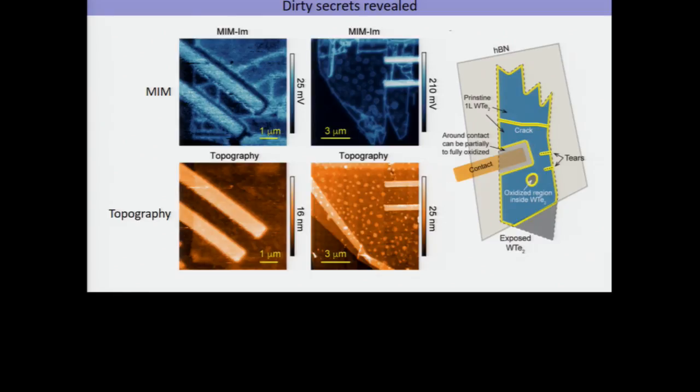But what prevents you from etching and then putting the contacts on, some sort of fab, etch, contact? There's a lot to be said about how to fab these devices, but the main limitation is you have to prepare it. The WTe2 can never see air. So you've got to think of a way of making contacts that doesn't involve exposing it to air in any way, and the only way you can do that is to prefab the contacts. If you had some fancy fabrication system set up in a glove box, you might be able to do it, but it's very hard. So basically, you pre-make the contacts.